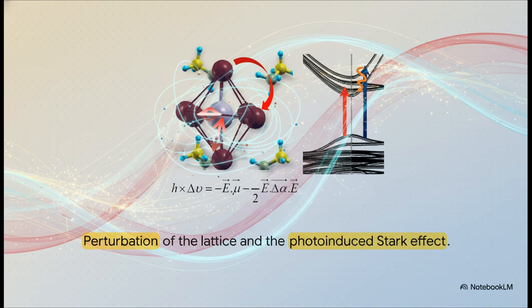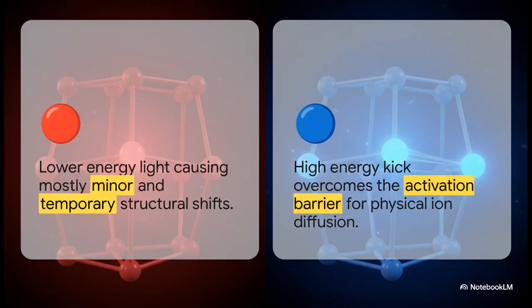And what they found using this technique was honestly incredibly surprising. They realized that the crystal doesn't just react to light in general. It reacts very differently depending on the exact color of the light hitting it. Let's break down those clues by comparing red light and blue light. Red light, at 630 nanometers, carries lower energy. It excites the electrons, sure, but the resulting structural shift is mostly temporary and relatively minor.